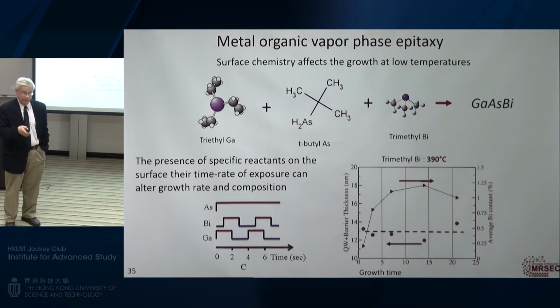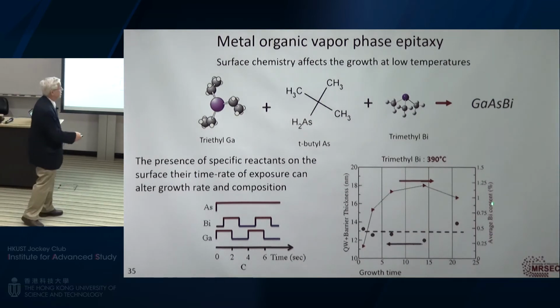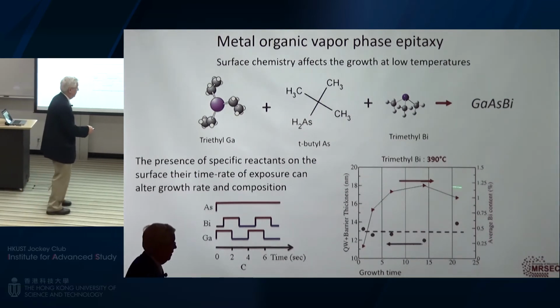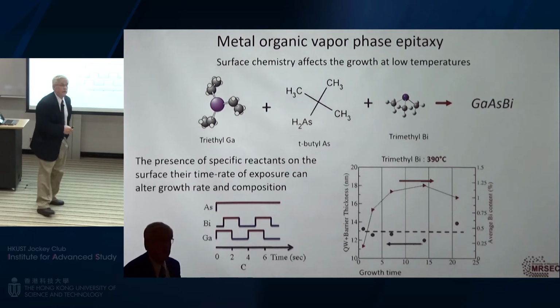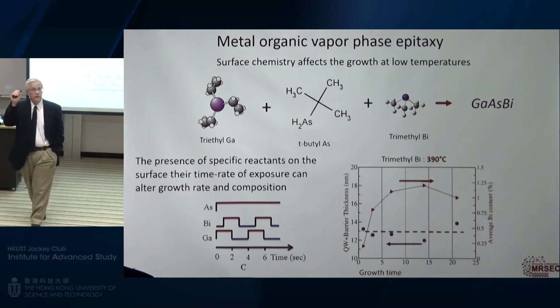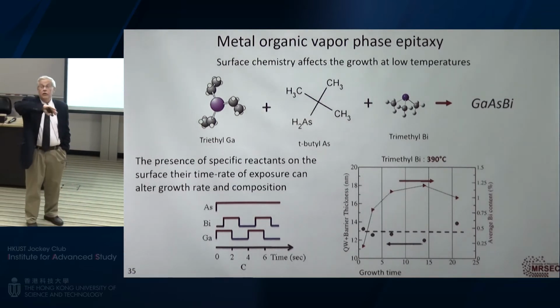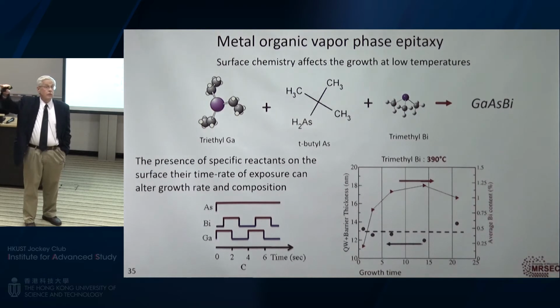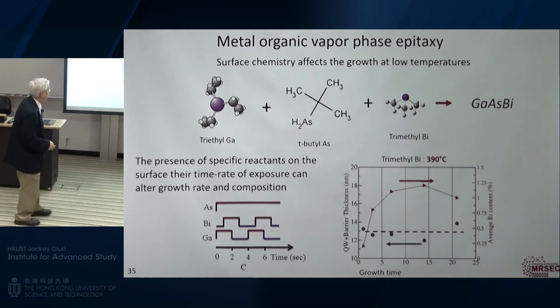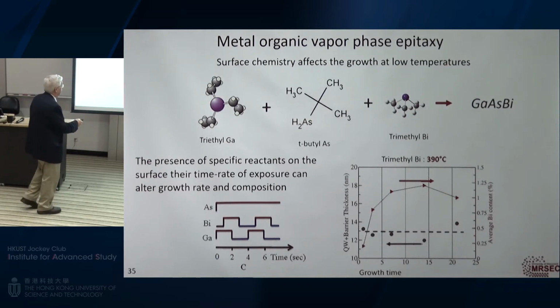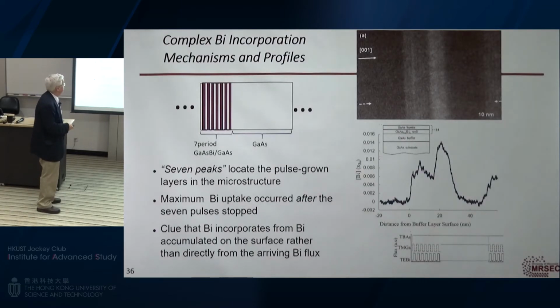But I'm also getting orders of magnitude more bismuth into the film, at least into what I grew. So the observation that you should remember is that I can start growing a film and it incorporates lots of bismuth, well above what it's supposed to have, but then it stops growing even though it's still in that reactive environment. So the question is what's happening, and how can we use that?